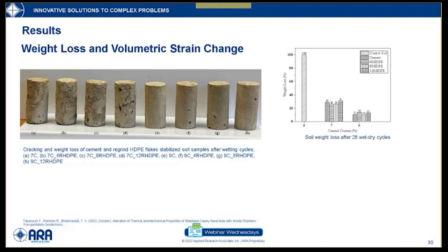And this right-hand side figure shows that when mixed with 0% cement, that is no cement in it, after just one wetting cycle, the soil completely failed. It failed on its own weight, like it cannot sustain or be run to the second cycle. And the weight loss for the 7% cement is more than the 9% cement treated samples. The minimum weight loss was observed as only 10% when mixed with 8% regrind HDPE.